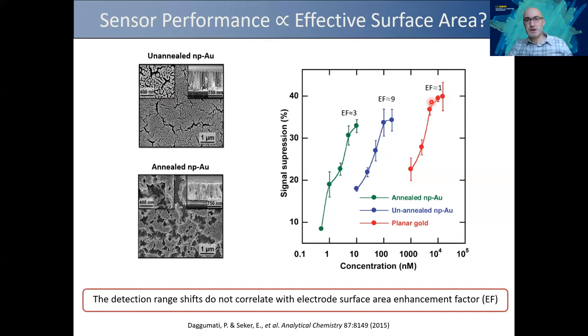But for different electrodes, we determined the surface area through an anodic stripping electrochemical method, and EF is the enhancement factor. So for gold, it's basically the control, just one surface area. It's the electrochemical surface area to the geometric surface area, right? It's the same for gold, there are no pores. If you go to the porous unannealed gold, it's 9 times more surface area. If you go to this annealed, basically sintered nanoporous gold, you have a reduced surface area compared to the initial porous electrode. What is interesting is that we got the best limit of detection with actually not the highest surface area. So while surface area plays a role, it's not the only factor that plays into the limit of detection.